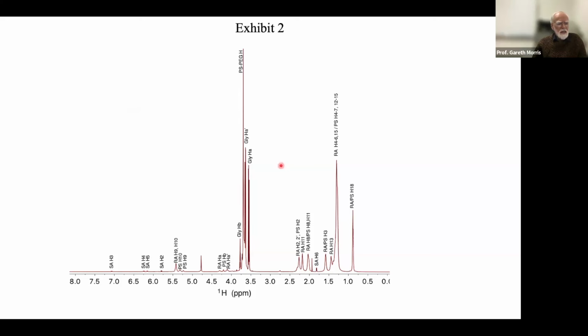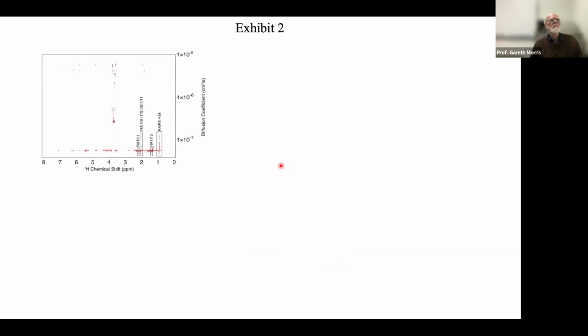Here's a second example, again from a reputable journal, in which a biphasic sample, which has got droplets in, was being studied by DOSY using a commercial software package. And here's the DOSY spectrum that was published, the apparent DOSY spectrum. And there are two things about this that really ring alarm bells. The first is that it's too good to be true. We have lots of diffusion coefficients that line up absolutely perfectly. We know that if our univariate analysis is giving us statistical uncertainty, that shouldn't happen. And the second is that we have two orders of magnitude of diffusion coefficient here. It's very difficult to get reliable data over such a wide range without using a very wide range of gradient values. So we should be suspicious.